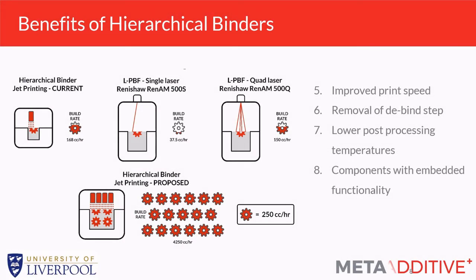We're also seeing that metal components conventionally used in additive manufacturing are produced by laser powder bed fusion, but if we can use binder jet printing, we can up the speeds at which we can produce bespoke metal components. So we could start to see other sectors taking this process and producing components that are bespoke in nature, but the speed is much faster and the cost is lower than, say, laser powder bed fusion. And that's because of removing all these processing steps and the fact that it's not a laser-based process, but it's a print head process.